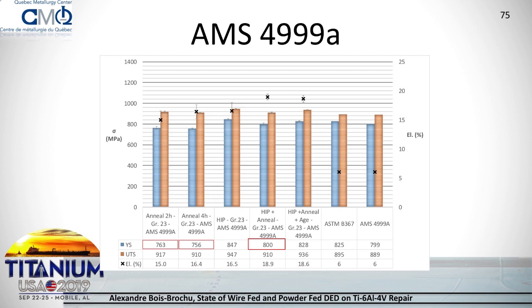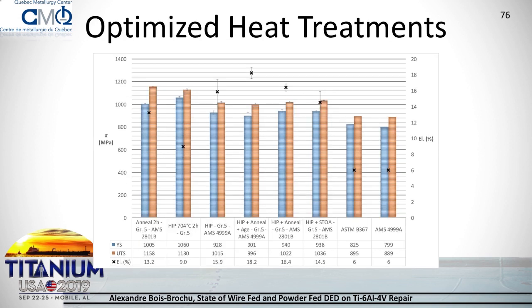Then you can perform some aging after HIP plus annealing, and you'll obtain a boost in mechanical properties sufficient to meet the standard. However, it's much more ideal to use a different heat treatment. If you look at the 2801 standard heat treatment, it uses an annealing at 704, so the temperature is much lower. And since the microstructure with powder-fed DED is fully martensitic when as-built, you'll be able to perform a martensitic conversion and thus obtain quite high strength.